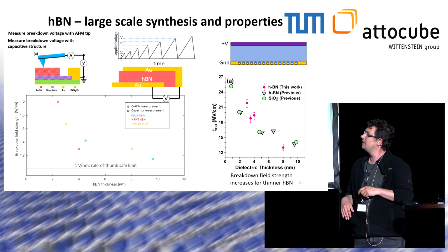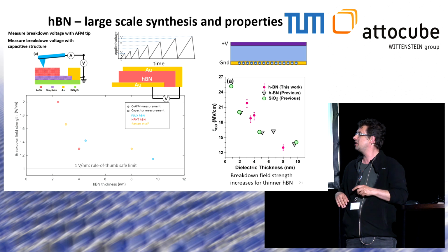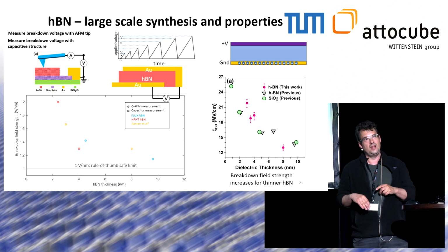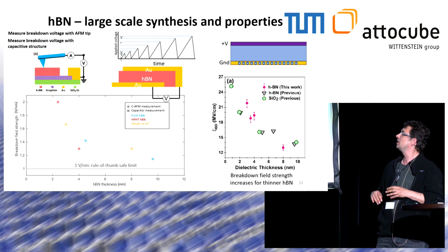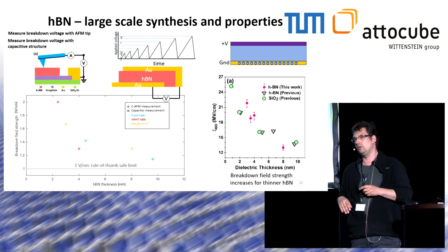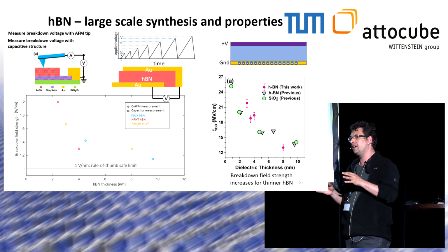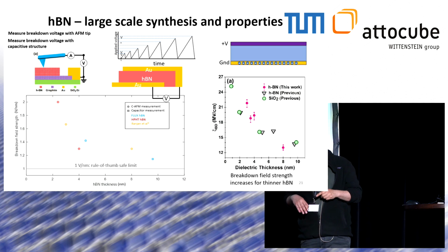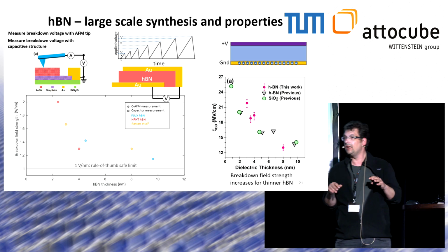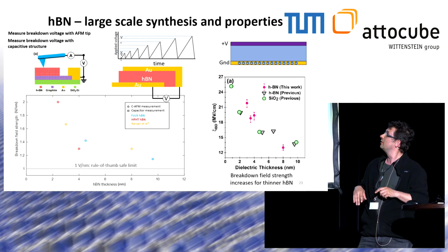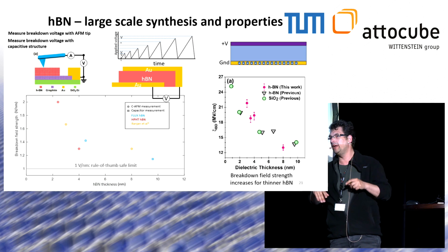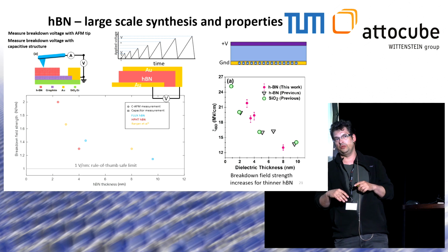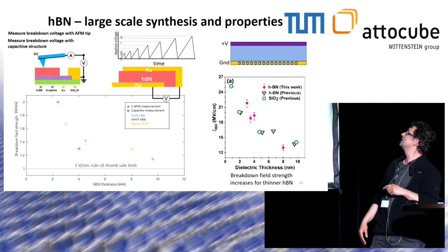For this material, typically the breakdown voltage exceeds about 1 volt per nanometer, which is comparable to high pressure, high temperature made hexagonal boron nitride. There can also be found, randomly, several of these quantum emitters, but it will be nice to explore more if it is possible from the flux to dope it and to control the formation of some quantum emitters in the system.